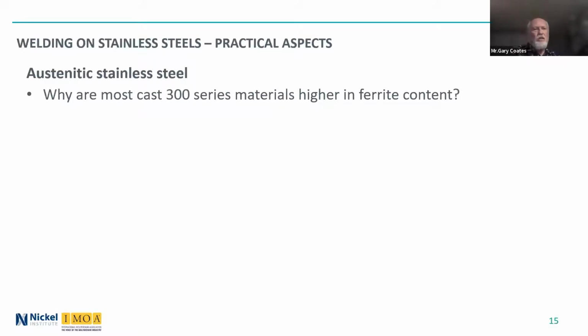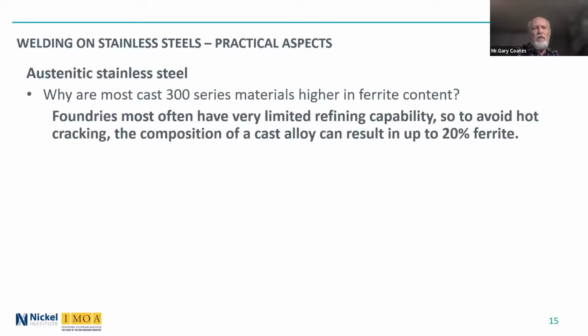So most of you understand that cast 300 series materials are higher in ferrite content than the plate, sheet, bar, etc. And that's because foundries most often have very limited refining capabilities. They can't take out things like sulfur, which, when present in larger amounts, can result in the hot cracking of the material. So they intentionally have a higher ferrite content, and sometimes they will make a 304L type cast material up to 20% ferrite. Very high levels, higher than you would ever see in a weld electrode.